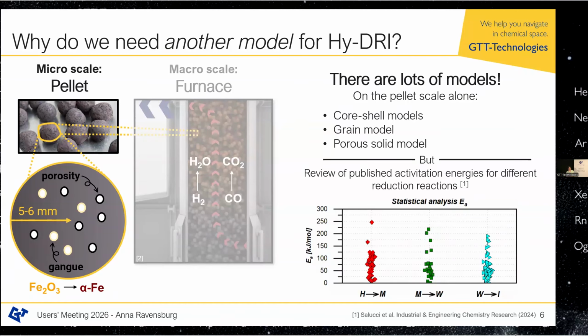Finnish group, and they published a review article. They looked at all of these pellet models, and then they took the values that these pellet models published about the activation energy of the 3 different reduction steps from Fe2O3 to Fe3O4 to FeO to Fe. And they plotted this activation energy nicely here, and all of them vary in the range that the actual value is in. So somehow, either one of these models is correct and all the others are incorrect, or all of them are a bit incorrect. The question is which one is correct.